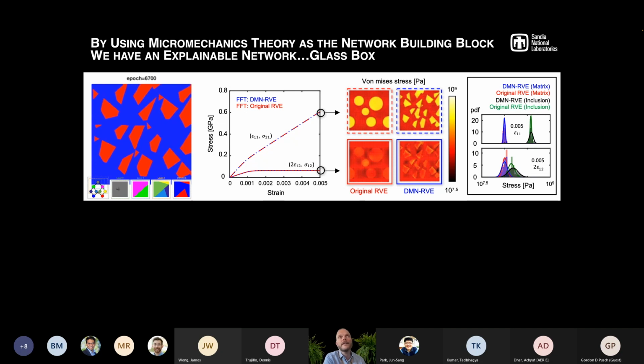And what you see on the right-hand side of your screen is based on this learned DMN RVE. What we learn along the way is that it's providing us a way to not only connect the macroscopic response as predicted by the network, but also to extract information on the local field distribution as predicted by the network. And what you see on the very right-hand side of your screen is that the distribution of local fields as predicted by the network corresponds almost exactly to the distribution of local fields as predicted by the direct numerical simulations.